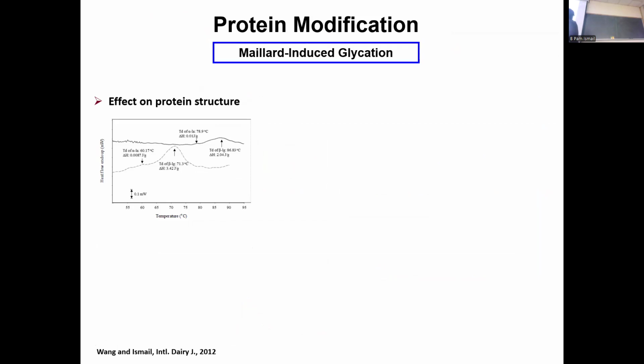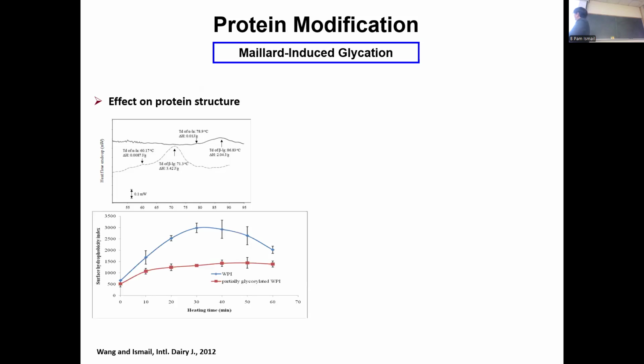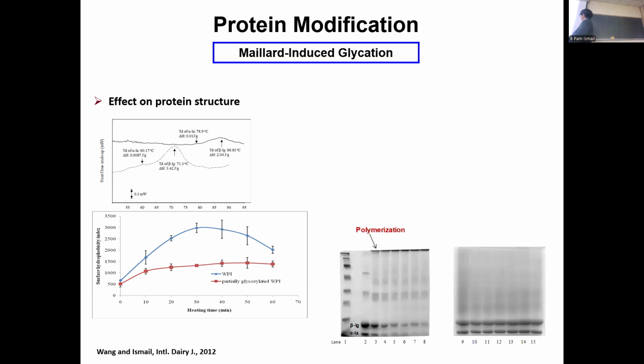And then we look at the effect on the structure of the protein. So when we glycate, the denaturation temperature goes up. In the case of whey protein, it went up about 15 degrees. So we induced thermal stability. And also surface hydrophobicity goes up a little bit after heating for 10 minutes and then it plateaus. Whereas whey protein isolate that is not glycated gets denatured and then polymerized. When it gets polymerized, we see a reduced surface hydrophobicity. And we look at the polymerization. This is the whey protein control. You see it builds up high molecular weight polymer with more heat treatment, whereas the glycated one does not.